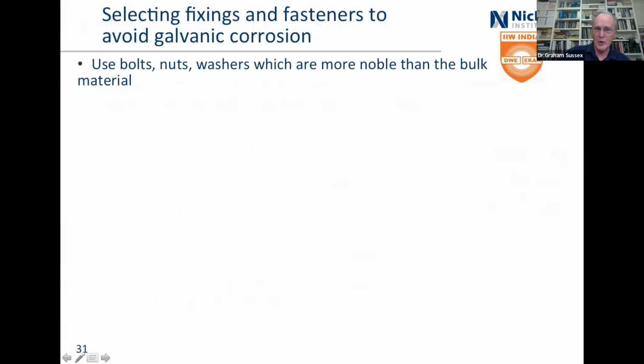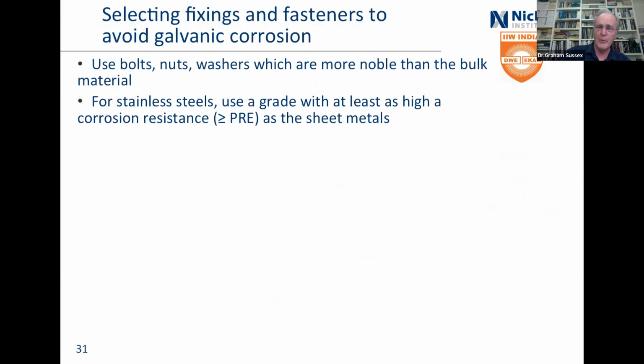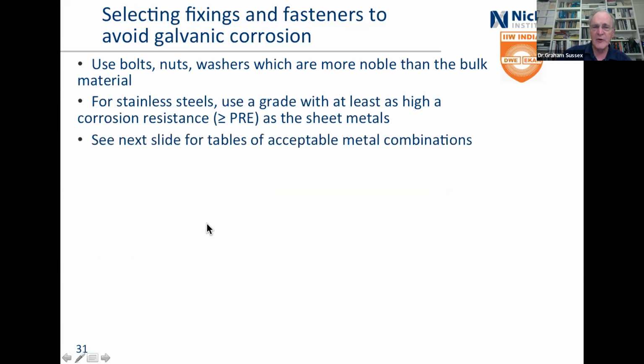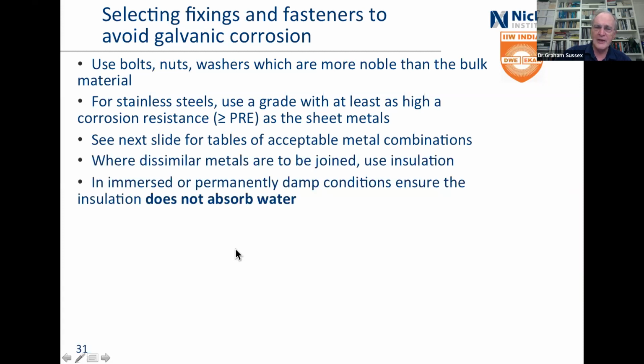So bolts, washers, nuts, they've got to be more noble than the bulk material. If you're using stainless steel on stainless steel, then you'd use the same or higher. But remember, again, PRE gives you the raw numbers, but if you're looking at stainless steels and the environment isn't too bad, then it's not a terribly good cathode.